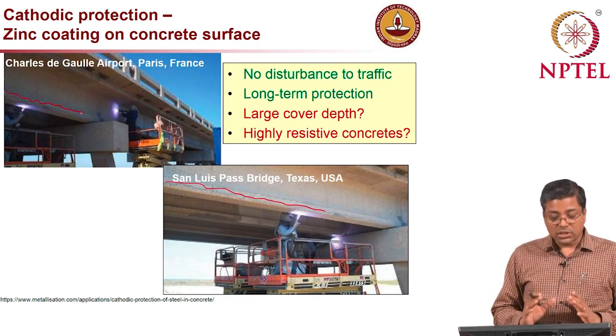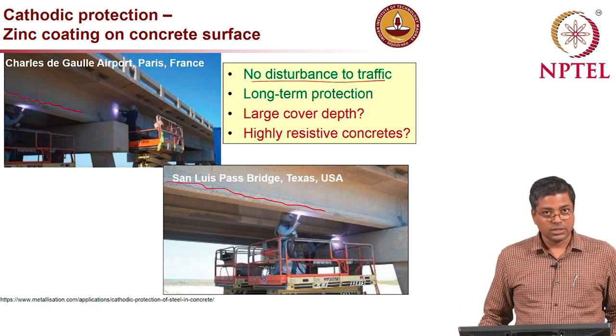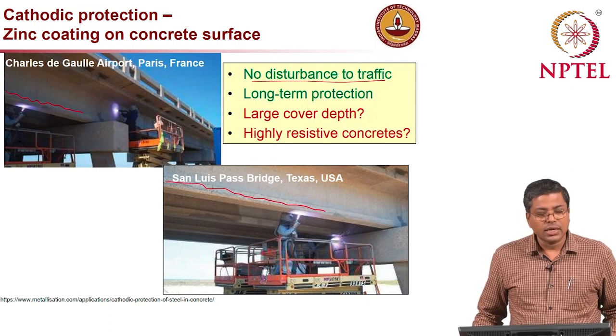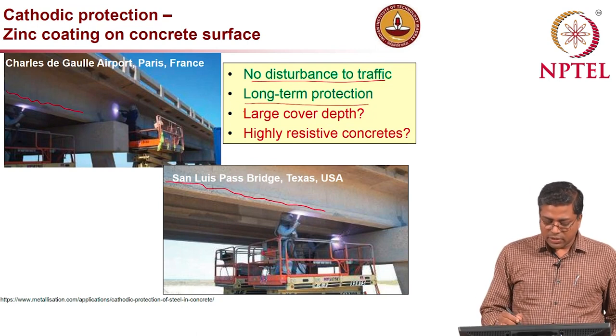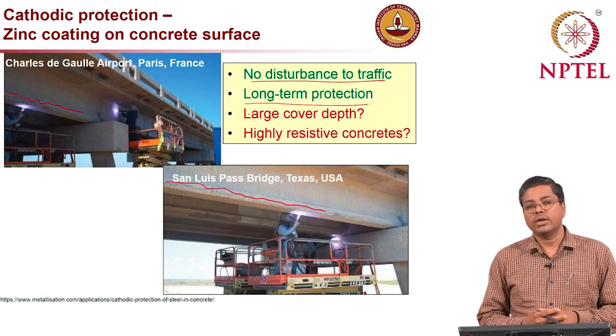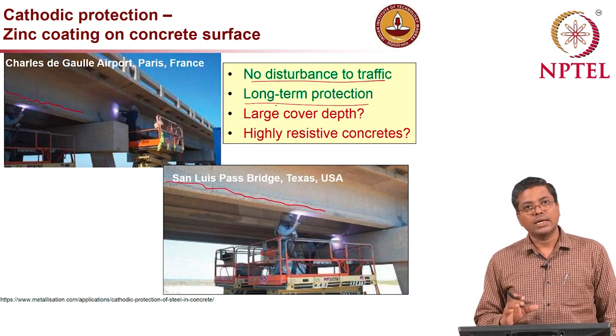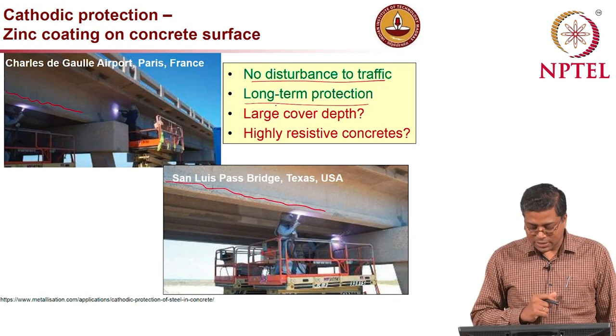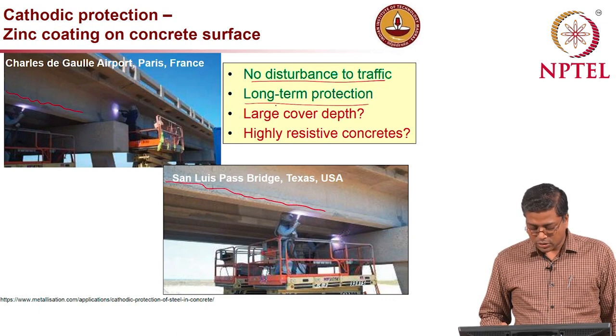A positive aspect of this technique is that it does not create much disturbance to traffic — it can be applied overnight. However, when cover depth increases or concrete resistivity increases, this technique does not work well. For larger covers or highly resistive concrete, this may not be a good technique to use.